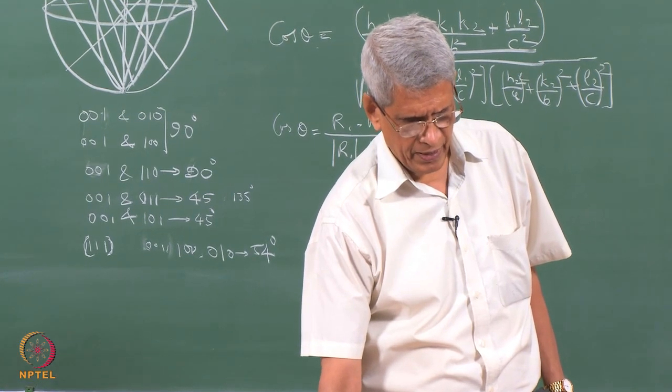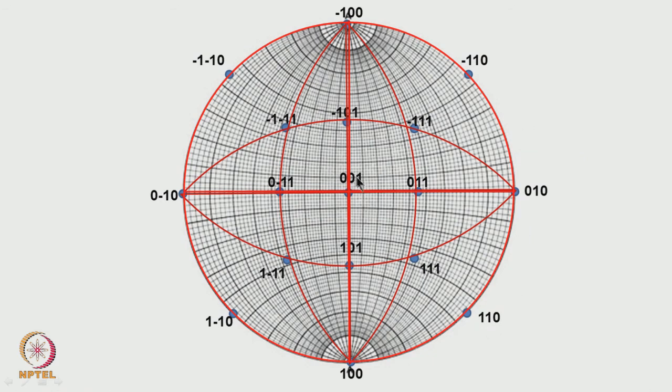What has essentially been done is that since we are drawing a stereogram of 0 0 1, the 0 0 1 will come at the center of the stereographic projection. So, we have taken the Wulff net, and on top of it we have kept a stereogram, drawn the primitive circle, and then marked these two axes, x and y, and marked this point as 0 0 1. By convention, the 1 0 0 direction has to come down here, and the 0 1 0 direction has to come in the y direction. Now, the angle between 0 0 1 and 1 0 0 is 90 degrees.